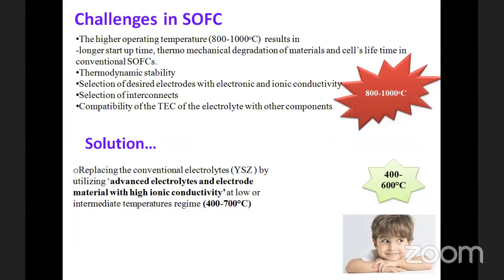But there are very many challenges in SOFC, solid oxide fuel cells. As I told you earlier, the main problem is the operating temperature is still very, very high, 800 to 1000 degrees Celsius. The second issue is that at that temperature, the thermodynamic stability is very, very important. So one has to deal with such things. And the third and most important thing is you have to select the desired electrolytes. The electrodes, like the anodes and cathodes, are very important in the selection. They should have excellent compatibility with the electrolytes. At the same time, the electrodes like the anode and cathode should have higher electronic conductivity and ionic conductivity, whereas the electrolyte should have excellent ionic conductivity and negligible electronic conductivity.